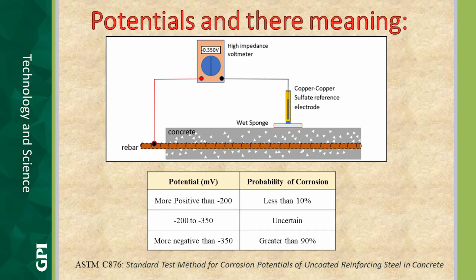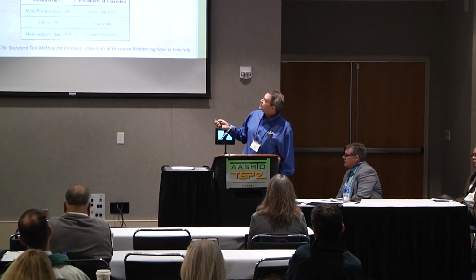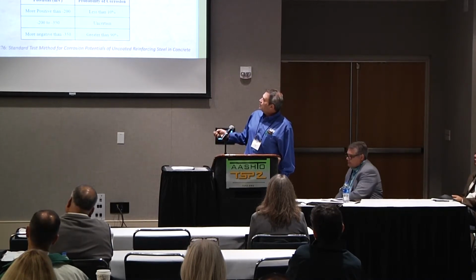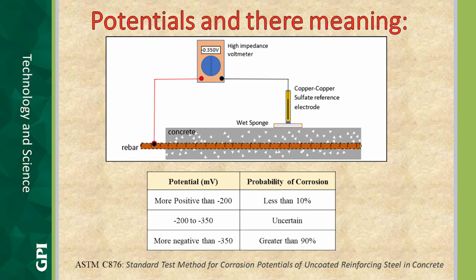So we've got the setup of what's commonly used up here. We've got a high impedance voltage meter. We've got a copper sulfate reference electrode on a wet sponge. We've got our rebar encased in concrete, and we make a connection to the rebar on the positive side and the reference electrode on the other, and we read the potential between the concrete and the steel. ASTM C876 gives us a probability table based on that potential that we can use as a general idea of whether corrosion is taking place or not.